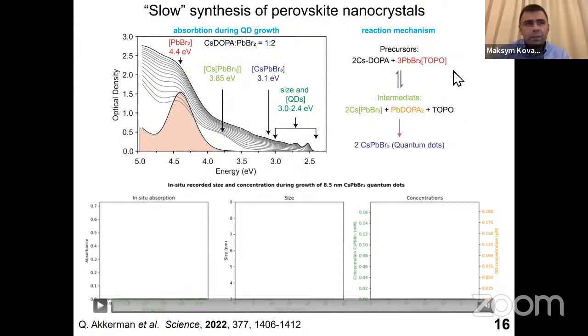The beauty here is that for lead bromides, you can actually observe all the relevant species in situ during the synthesis. The precursor itself, then at slightly smaller energies, you observe this intermediate, and then finally you observe the quantum dots. And so just by measuring the in situ optical absorption spectrum, you can recalculate these features, their intensity, their optical density, into the population of every species, so you can track the mechanism of the reaction.